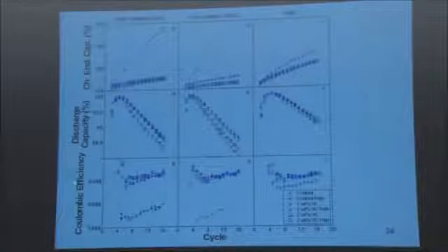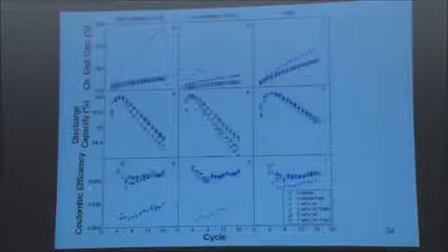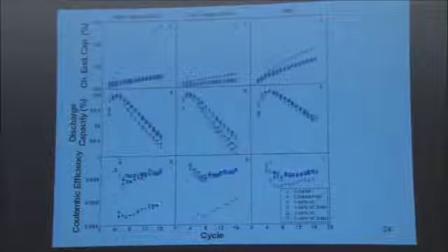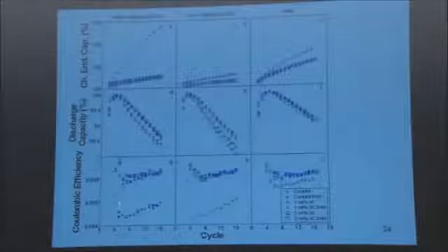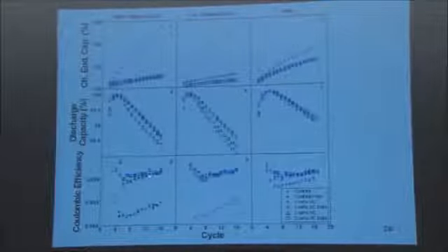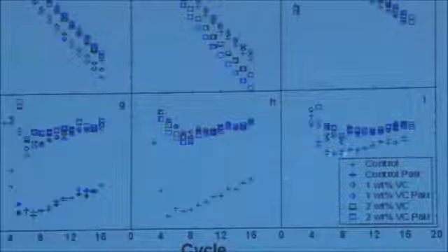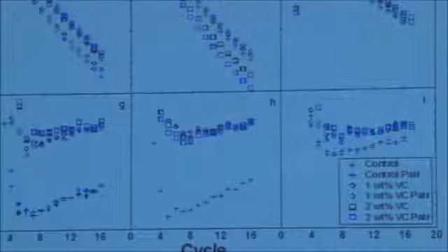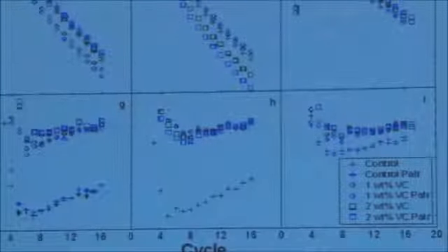If you look at the Coulombic efficiency and look at the scale here, and look how repeatable the pair cells are. These are commercially made cells. Without vinylene carbonate, the Coulombic efficiency is poor. And with vinylene carbonate, the Coulombic efficiency is much better. And with a nickel manganese cobalt positive electrode, without vinylene carbonate, it's a much better situation. Why is that? I don't know. And adding vinylene carbonate improves the situation over here.